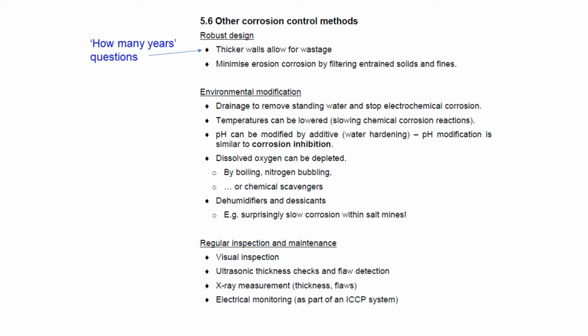This is something which effectively does happen in salt mines, in which you can be quite surprised that in your metal steps going down into the salt mine there's really bad rusting, but within the salt mine itself there's very little corrosion of even exposed metal objects. That's because the salt is such a good desiccant, it pulls so much water out of the air, there's no surface layer of moisture on the metal to allow electrochemical corrosion to even happen. Of course, you don't have to be in a salt mine for this to happen. Any dry air environment could be made deliberately dry so that this would be protective.